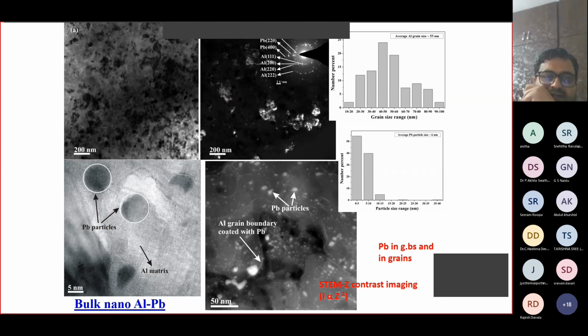And then these are the microscopical details. We have a high resolution TEM here to understand the particle size of lead, not the grain size. And also, this is a different kind of imaging technique where you see that there are some boundaries that show some kind of white regions. This technique is based on TEM. We call it STEM, scanning transmission electron microscopic mode. And this is Z contrast imaging. That means the contrast varies based on the atomic number of these elements. For example, the bright regions are from lead and the dark regions are from aluminum. Aluminum atomic number is 13 and lead atomic number is about 82. So therefore, lead becomes brighter in this.